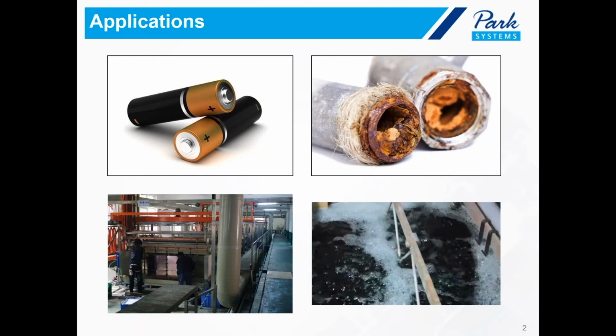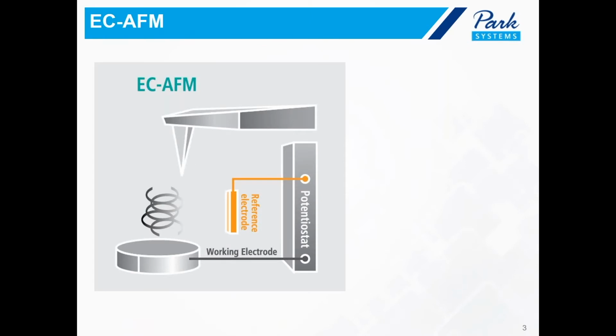Given that good deposition mainly depends on the substrate surface morphology, a technique that can measure this characteristic and monitor the electrodeposition process at the nanoscale is greatly needed. To overcome the shortcomings of ex situ techniques such as SEM or slower techniques like STM, electrochemistry has been combined with atomic force microscopy, and EC-AFM was introduced. This technique allows users to perform in situ imaging and visualization of changes in surface morphology of the sample being studied under a certain electrochemical environment at the nanoscale.